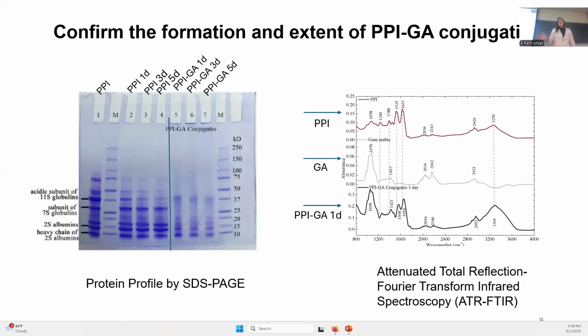So the first step was to confirm that the PPI conjugated with the gum arabic. For that, they used SDS-PAGE and FTIR. For SDS-PAGE, one indicator that this reaction occurred, for the authors, was soluble aggregates on top of the gel, because it wasn't seen before when they incubated just the pea protein. Another indicator was the fading of strong bands seen around 15 and 28 kDa. They were strong before, but after incubating with gum arabic, they were fading. So they concluded that those are among the main subunits involved in the reaction.